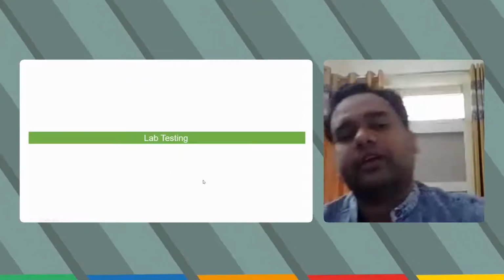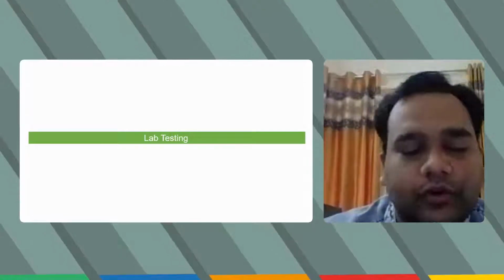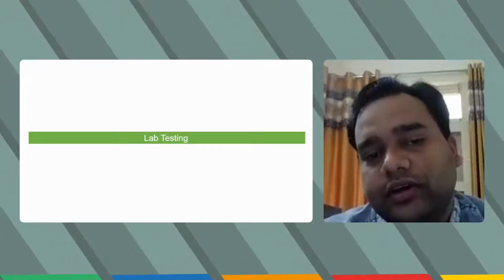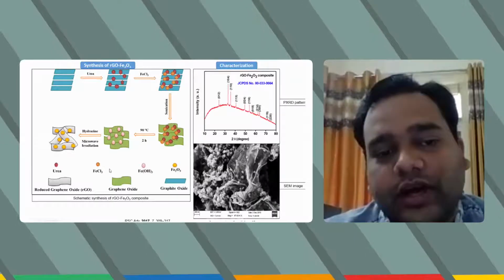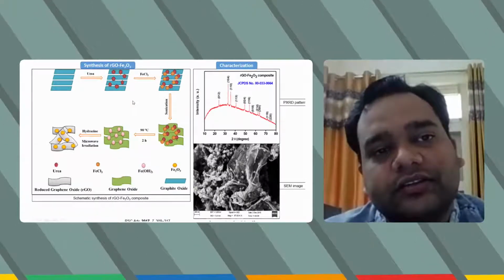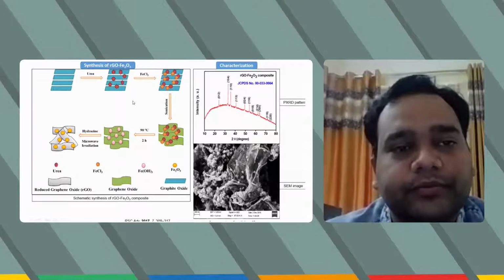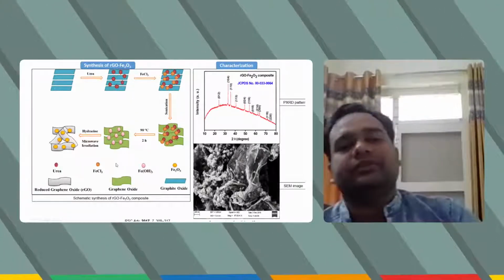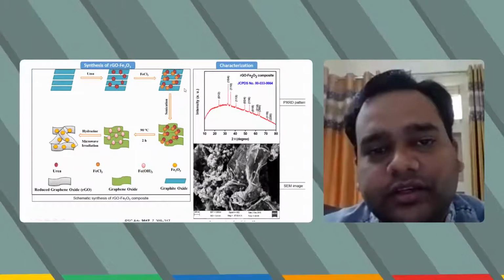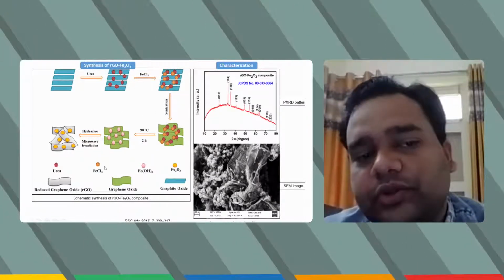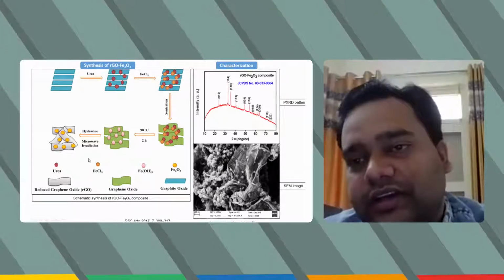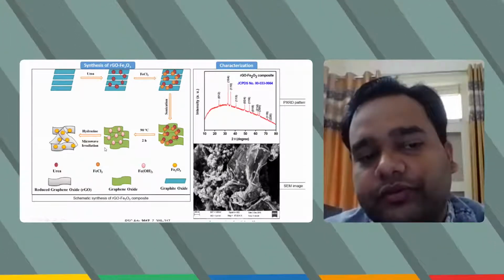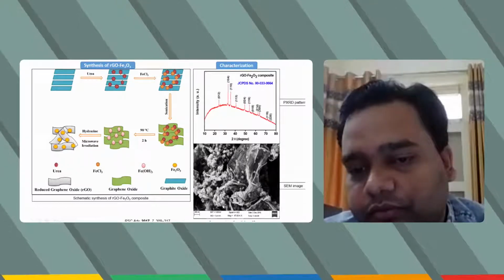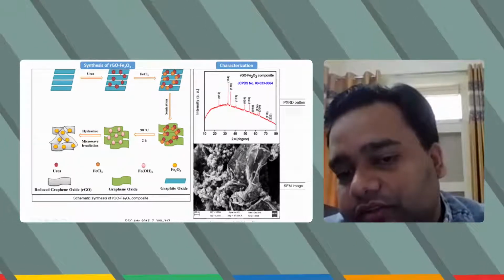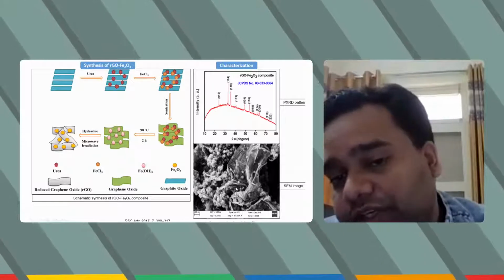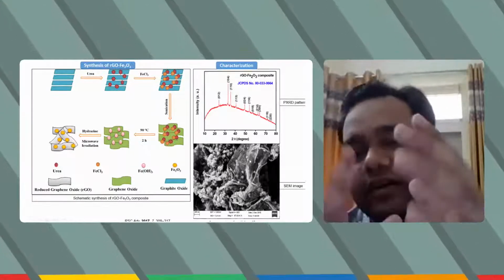So when we prepare our material, before going for practical application, we do lab testing. In my PhD, I developed various materials. You can see one of them is rGO-Fe2O3. We synthesized this rGO-Fe2O3 by a very simple method, in which first we reduce FeCl3 into FeOOH, and then we reduce it by hydrazine under microwave irradiation, and we get this beautiful morphology of rGO-Fe2O3. You can see small Fe2O3 nanoparticles which are properly embedded within graphene sheets.